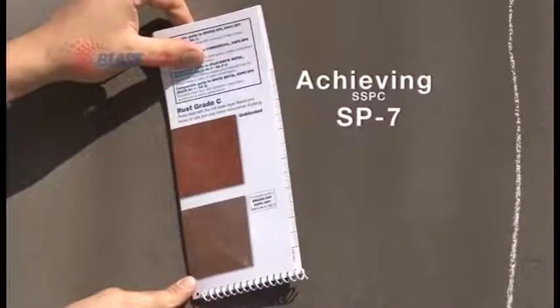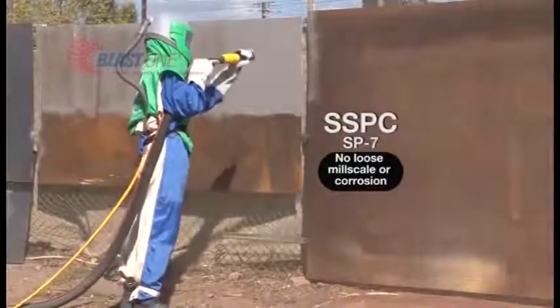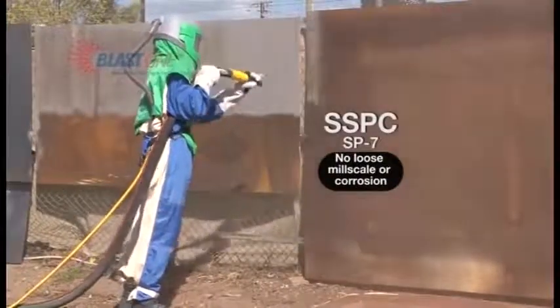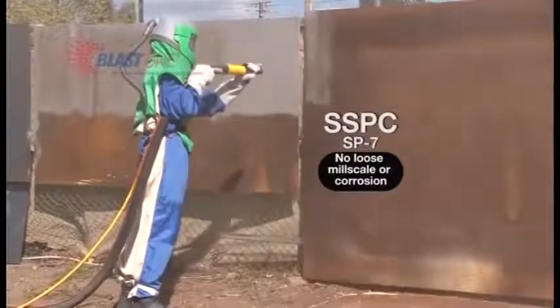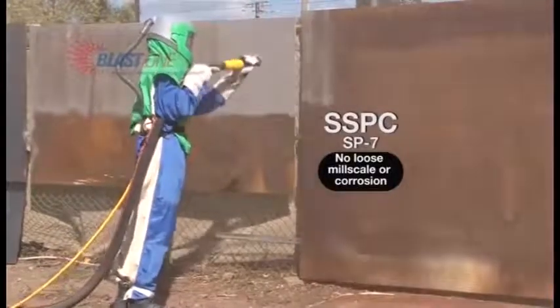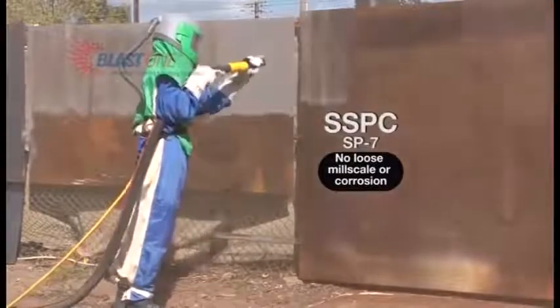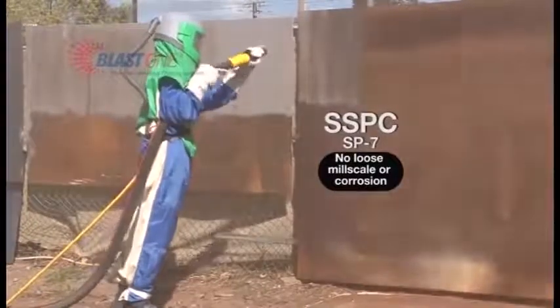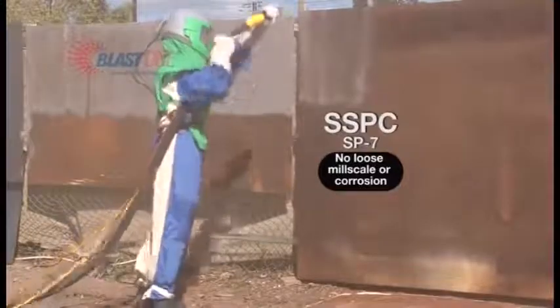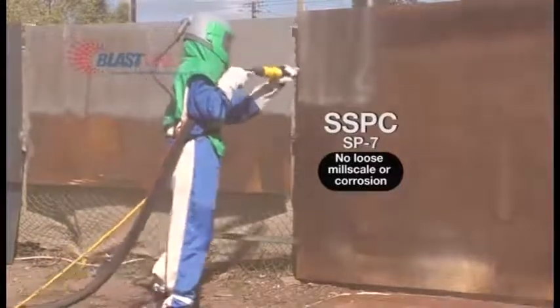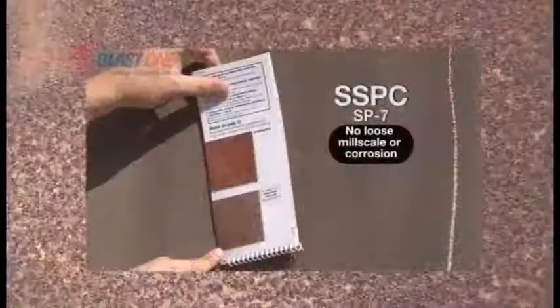How to achieve an SSPC SP7. The specification for SP7 is the removal of all loose surface contaminants. SP7 can be achieved with a rapid but thorough brush off of the substrate. The nozzle moves very quickly to remove all loose mill scale and contaminants. As you can clearly see on this grade C substrate, SP7 has been achieved.